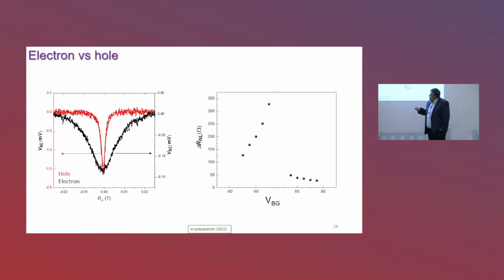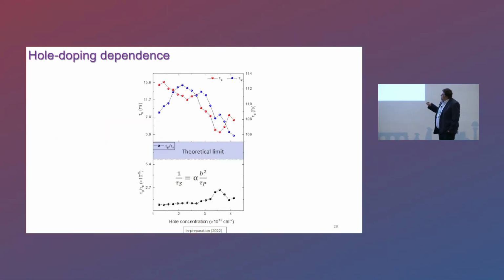So what we do see is that the mobilities for electrons and holes in our device were almost identical, around 800 cm². But whenever the spins are carried by holes, we see almost 10 times better signal compared to the electron case. And when we study the spin relaxation times as a function of the hole concentration, as you can see, these spin lifetimes are exceeding 15 nanoseconds, which is, I think, one of the highest ever measured.